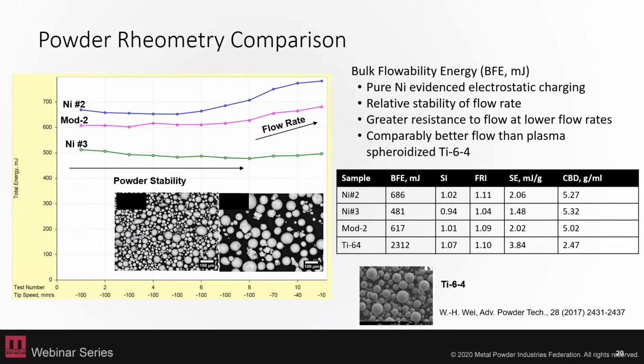And then, just a qualitative comparison, not a quantitative comparison, to a titanium 6-4 powder, you can see that the bulk flowability energy especially is different for titanium versus nickel in this case, and that can give you an indication of how this powder might perform in your powder bed or your directed energy deposition AM machine, and how, if you're switching materials, you might need to change your approach.